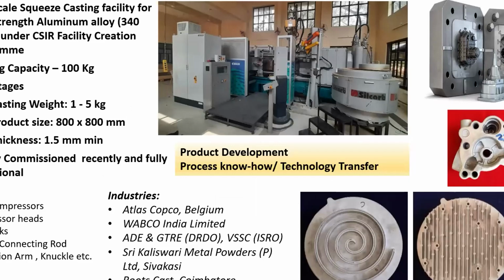And we have a pilot scale squeeze casting facility at CSIR NIST, where we have a 100 kg melting furnace, and there's an auto ladler system. So this ladle will take the metal of required quantity, pour it into this one, and there is a die like this, and the metal will be pressed into that, and once the component shape is formed after solidification, then we remove it. And normally the casting weight capacity is 1 to 5 kg, and the product size is 800 by 800, and the thickness is around 1.5 mm.